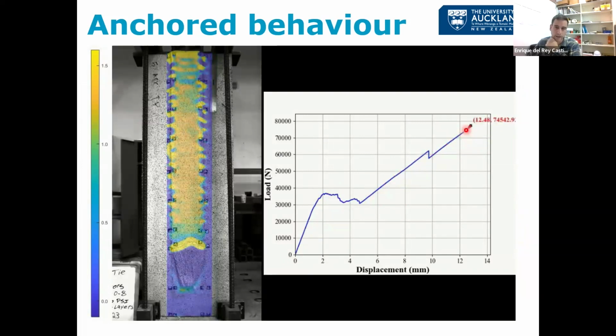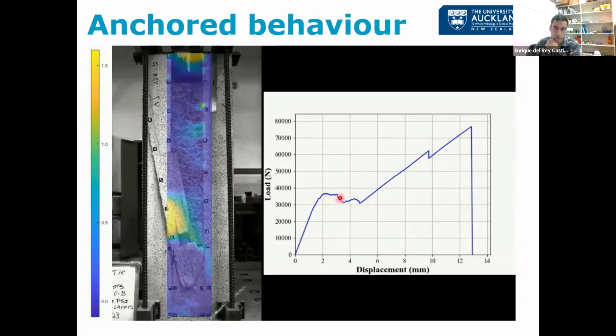So the anchor is giving us extra force, like over twice as much force, right? 35 to 75. But it's also giving us a lot of extra deformation capacity, from 2 millimeters, the start of the inelastic response, all the way to 12.5 or 13 millimeters. So the deformation capacity that the anchors are providing is huge. We still want to design to that level.